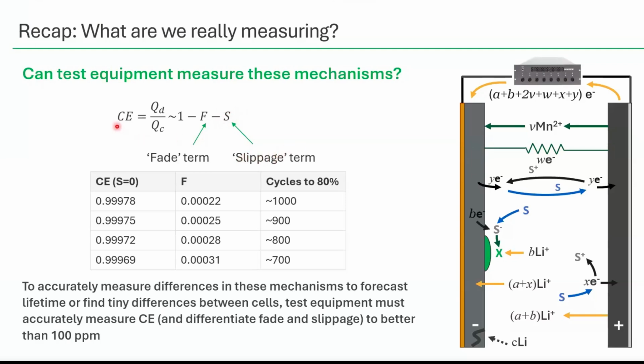If you can measure coulombic efficiency very accurately, it means you can also split these things out and look at fade independently of slippage, because really these two things contribute to your coulombic efficiency. The mismatch between your charge and discharge has contributions from both. So in all of these case studies, we're going to look at one, the other, or both, and try to get to the underlying mechanisms quicker, because we have the required accuracy to do it.